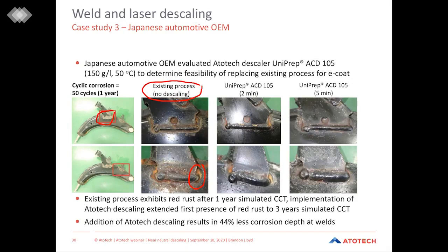And lastly, as we move to the Uniprep ACD 105 application at 5 minutes, we can see an even greater reduction in the amount of rust along the welded area. The existing process exhibits red rust after about 1 year simulated cyclic corrosion testing, and the implementation of the Atotech descaling extended the first presence of red rust to 3 years simulated cyclic corrosion testing. The addition of the Atotech descaling ended up resulting in about 44% less corrosion depth at the welds, which is quite significant for them.